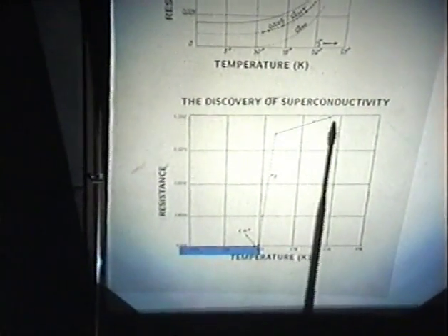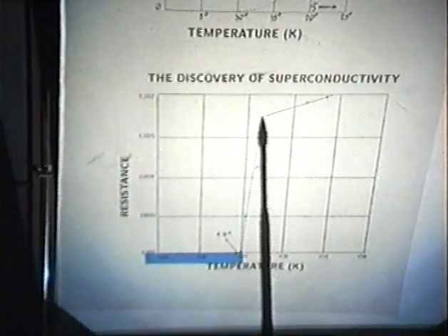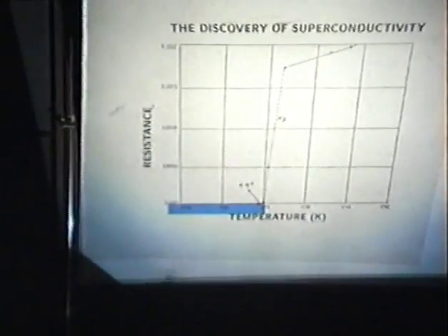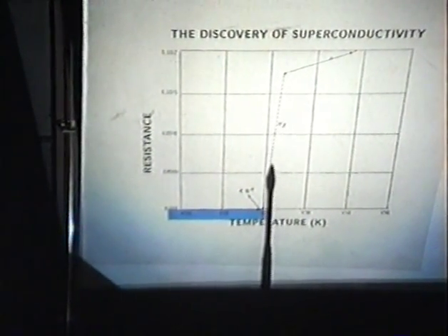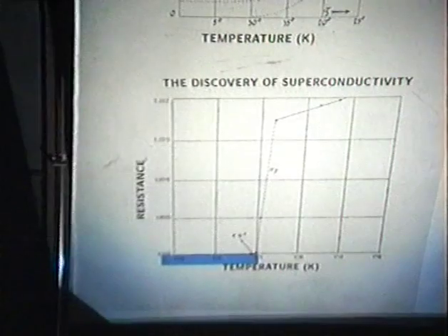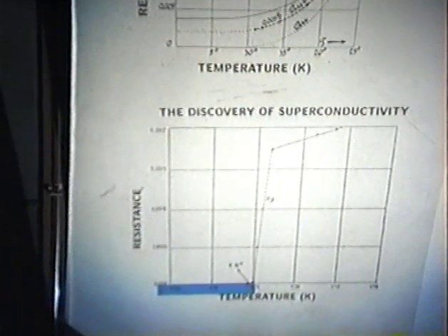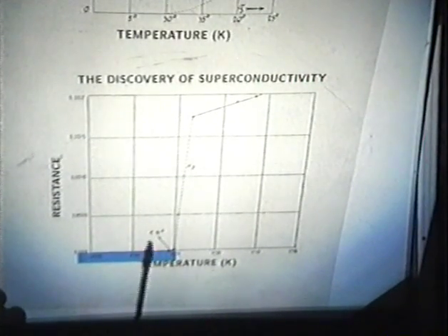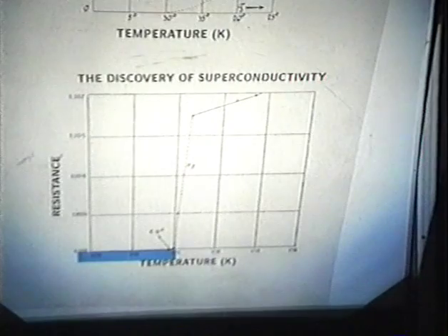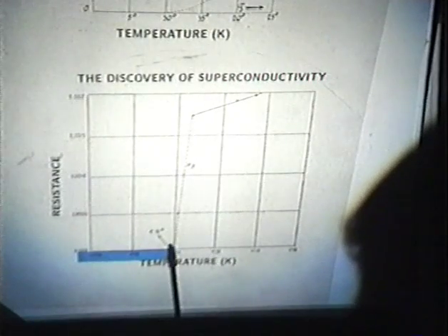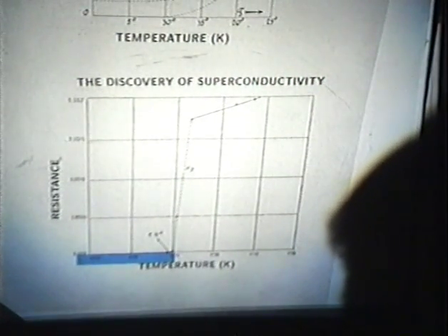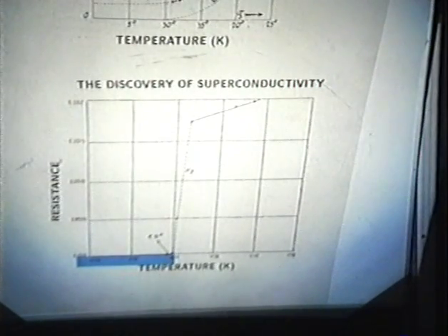They followed the resistance of the mercury down, down, down, until suddenly at 4.2 Kelvin above absolute zero, the resistance suddenly plunged right down to below the sensitivity of their resistance measuring apparatus. They could only put an upper limit on it, and this was quite startling, because instead of the nice gradual decline that they were looking for, there was evidence that something new had happened to the material and that it had gone through some kind of phase transition. And there are a lot of other strange phenomena associated with this as well.